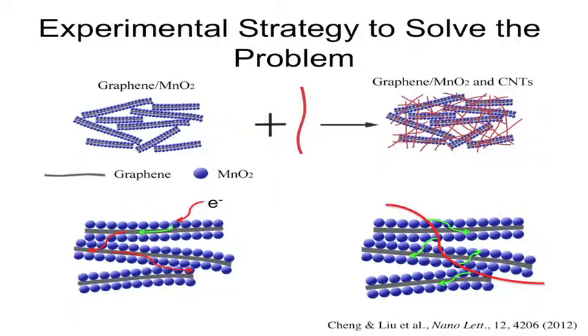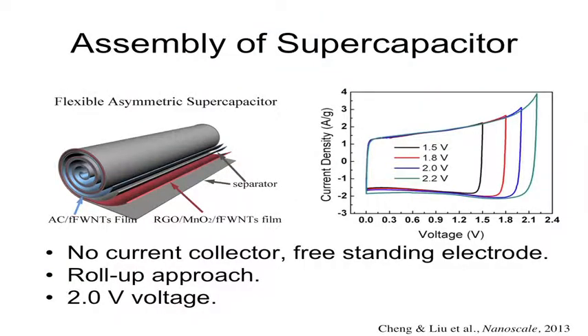The strength of this material is as good as nylon film. See, this is the strength of this composite material that we make that's self-standing, compared with nylon film. It's comparable. So we actually have a very good, strong, and highly conductive film that we can use for energy storage applications. And we actually did that. I'll show you. We have this film. They are very flexible already. We put a separator there, and we put another layer of similar film, and just roll it together, and we get a capacitor.